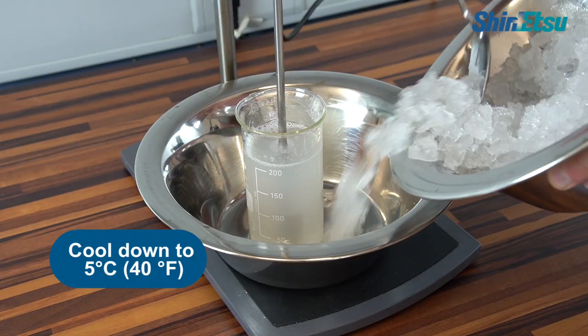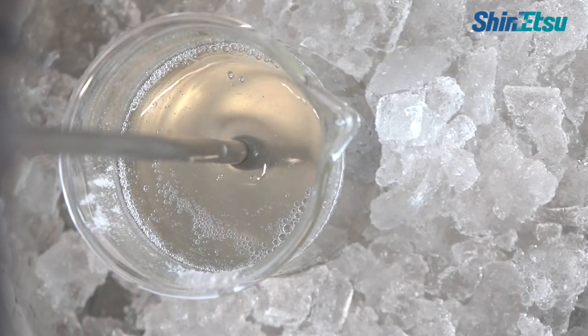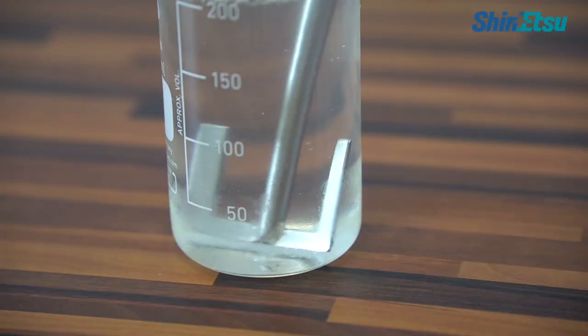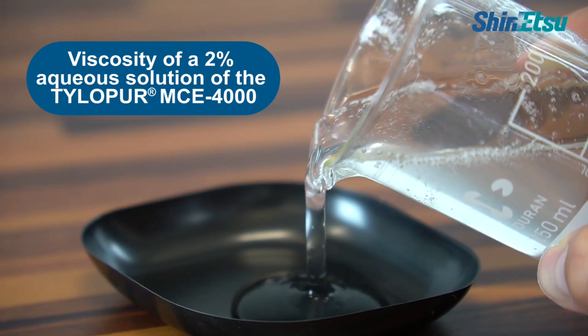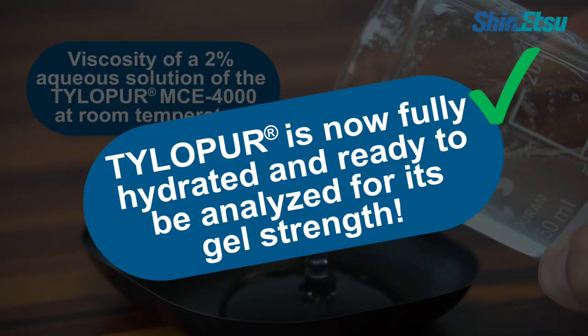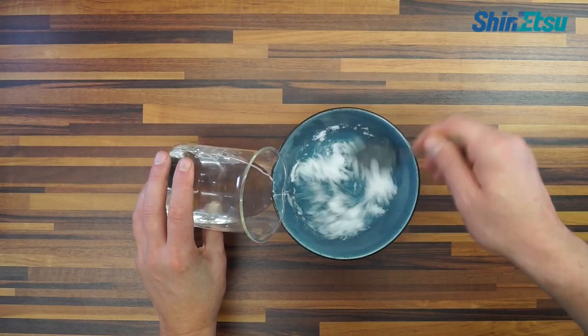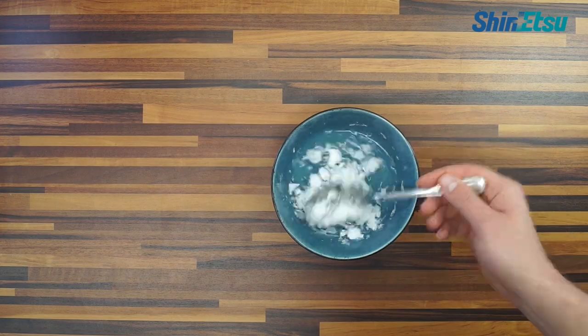The remaining water is added and the solution is cooled down to 5 degrees Celsius. Tylopur is fully hydrated and functional once the solution becomes transparent. A pure solution of Tylopur is therefore made by adding the powder to hot water. A direct addition of pure powder to cold water should be prevented, as this leads to lumps.